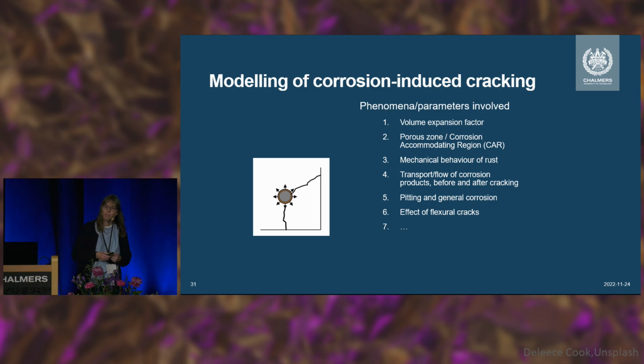You need to know if the corrosion products can escape. They may be transported even through the porous media, which concrete is, and even more so when you get cracks. Can they escape through the cracks? And are the corrosion products even soluble, so they can be washed away? We also have the effect that, especially if you have chlorides, you will get something like pitting corrosion, so you will get not just corrosion all the way around, but more at certain spots, both around the bar and along the bar. So these will really influence the crack pattern. And there's the effect of flexural cracks, the 3D effect, and so on. So there's so much in this.